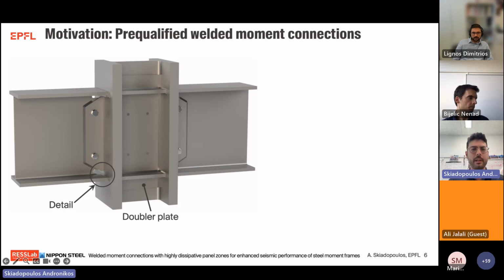The lessons learned from the 1994 Northridge earthquake led to what we have today as pre-qualified welded moment connections, as characteristically shown in this schematic here. To ensure limited deformations within the panel zone, doubler plates are often imperative. Note here that these doubler plates are welded to the column web, and therefore the shear resistance of the column web panel zone is increased, and we ensure an almost elastic panel zone response.